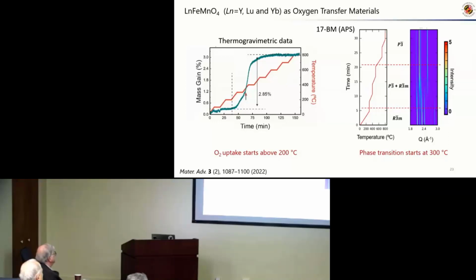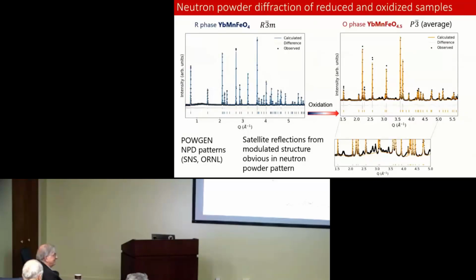So we can see here that the phase transition, which is fairly complex, is first order because you have phase coexistence here of two different phases. This is the time versus some intensity in Q. So now I plot in Q. My very first plots were in d spacing. I know you don't like that, Brian. So I've reformed over the years.